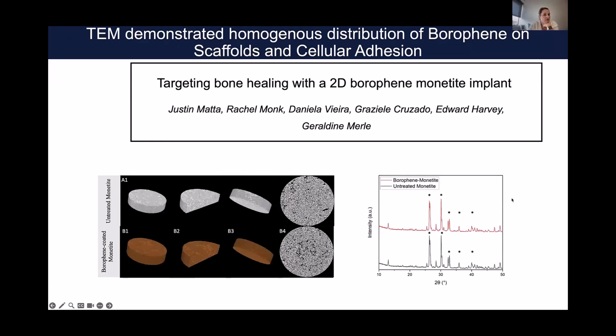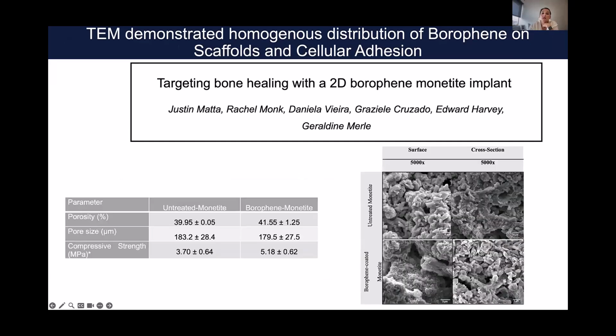So once again, when you add the borophene, you have no change in the crystallinity of your material. Again, you have a better mechanical strength of your cement, with not much difference in terms of porosity and pore size. So here you have the scanning electron microscopy image of your implant, with and without borophene. So this is without and this is with, the surface and the cross section. And here you can see some borophene nanosheets inside your cement.